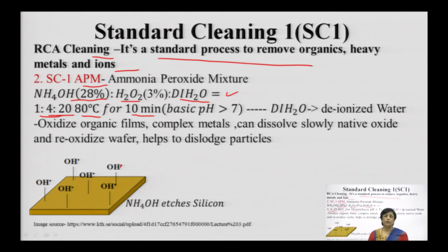But here also a word of caution: you must note that the quantity of ammonia we are using is very small, because there is a tendency of NH4OH to etch away the silicon, and you do not want that. If carried out for a longer duration, this can create micro pits on the substrate wafer, and you do not want that either. So, you need to do it precisely for a particular duration, and the temperature and everything has to be very controlled and precise.